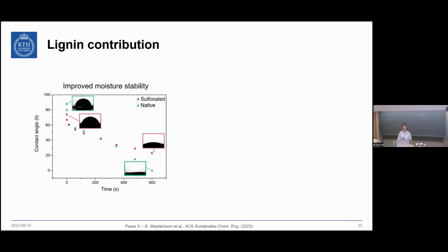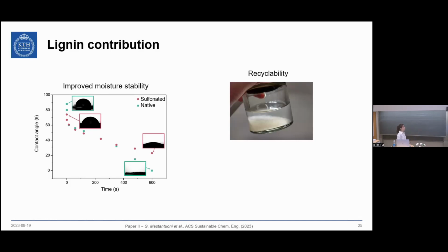And this comes actually not really from the chemistry, but from the morphology of the sample. So we increase the density, which means that in the end it will be more difficult for the water to seep through the surface. When the chemistry actually comes into place is for recyclability, because we have introduced a lot of sulfonic groups in the structure that repel each other. So if we then submerge the film in water and we leave it soaking for around 1 hour, then it's possible to easily fibrillate the sample.